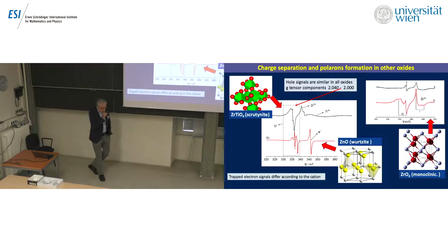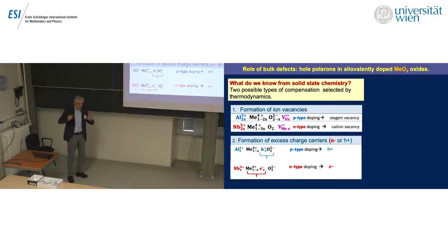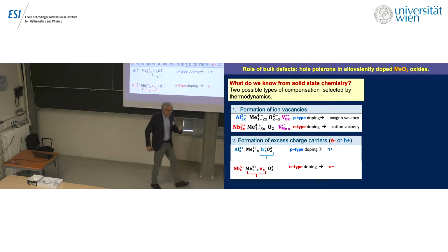Now I would like to anticipate something that will be useful in the following. There is another way to generate polarons, that is to introduce a single polaron in a system by doping, and this is a typical question of solid-state chemistry, so I will give you some information because it's a tricky problem. If in a semiconducting system you introduce an extra electron or an extra hole using a suitable chemical doping, you have two possible reactions, okay? Let's imagine to work on this kind of system, so titanium dioxide, zirconium dioxide, and you can put aliovalent dopants, which means to put an element with a different charge, and so you can put aluminium, one less, or niobium, one more.